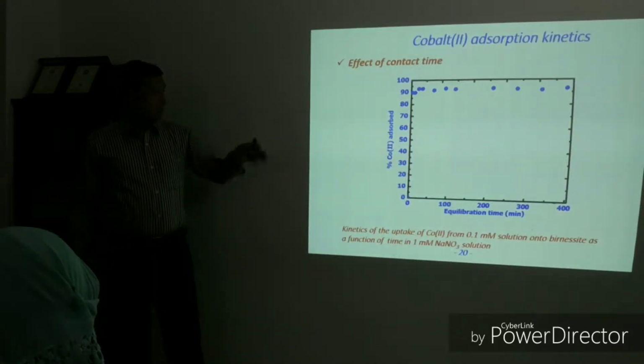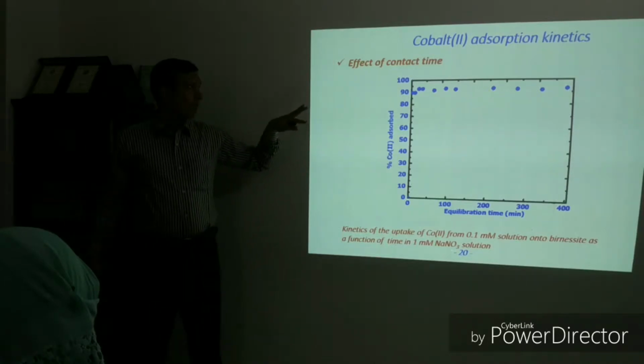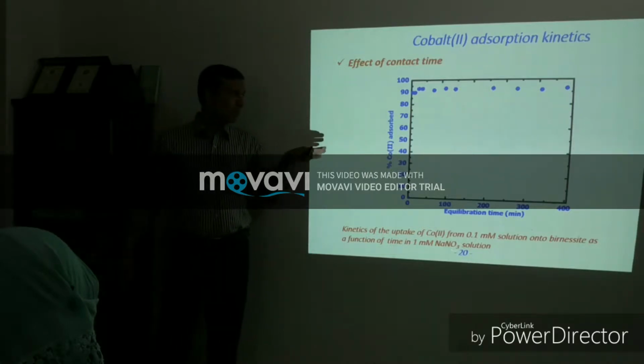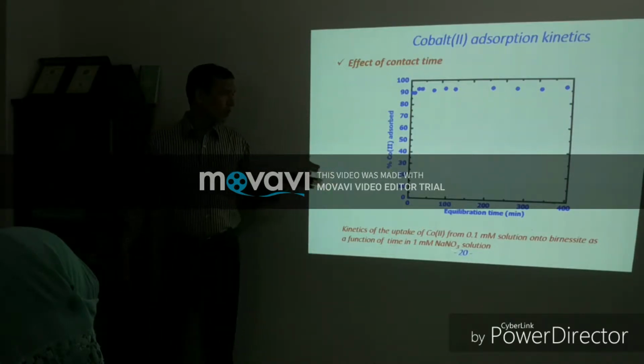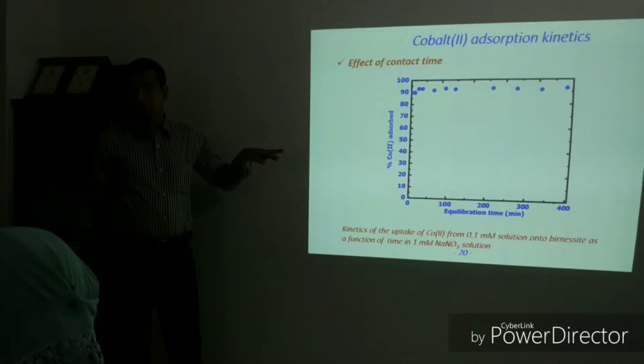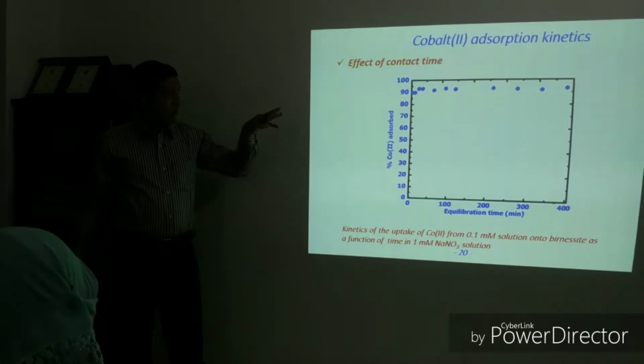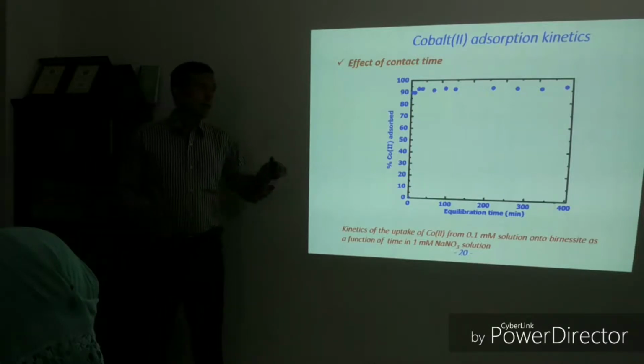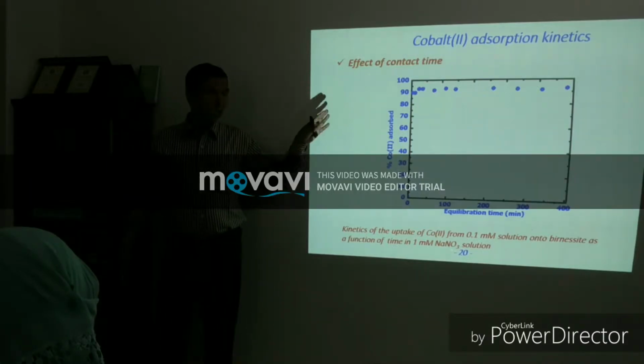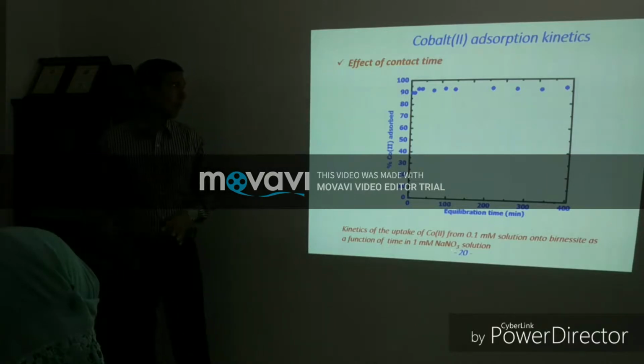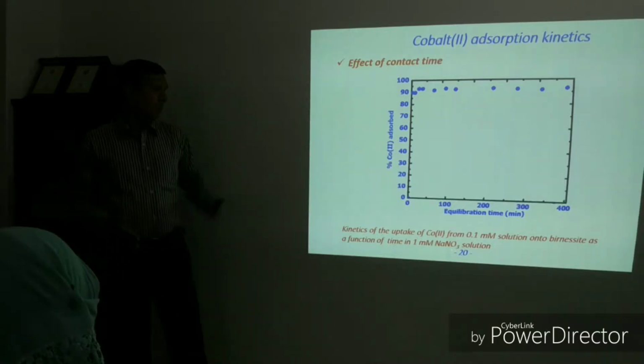Then, this figure shows a typical example of cobalt adsorption kinetics. From this result, we see that the amount of cobalt adsorbed increased very rapidly with increasing contact time and reached equilibrium within less than 20 minutes. It means that chemical adsorption rather than physical adsorption takes place, and adsorption is a very rapid process. Almost similar results were found for other substrates.